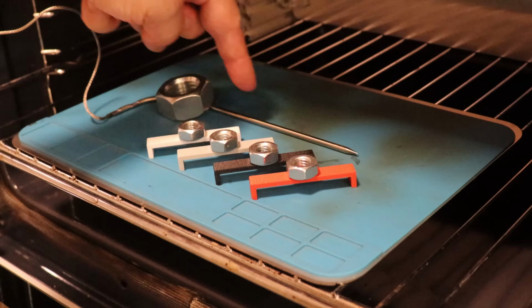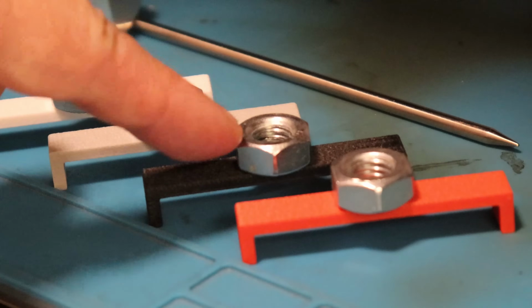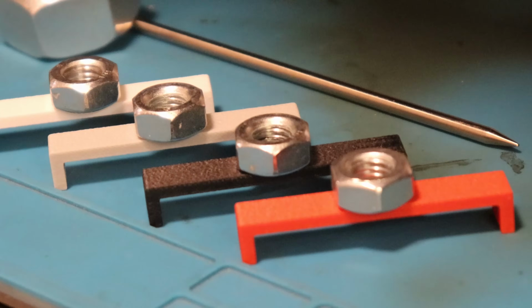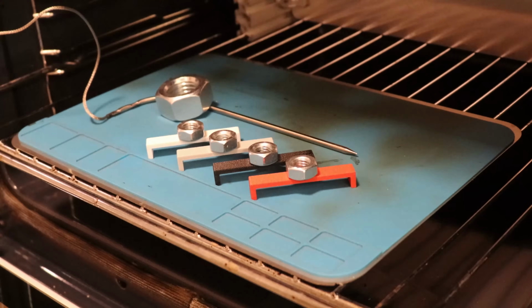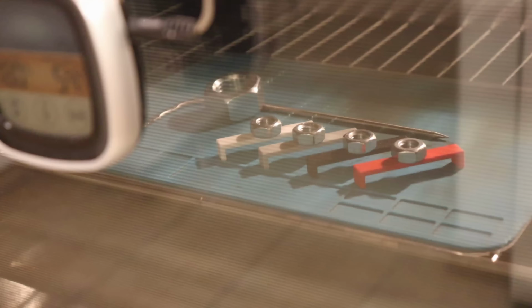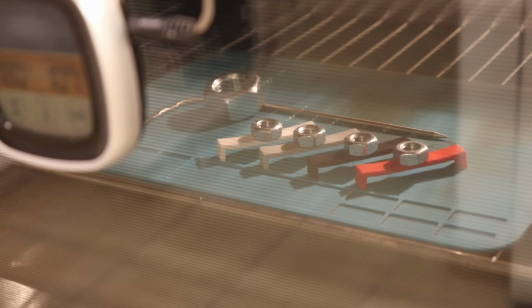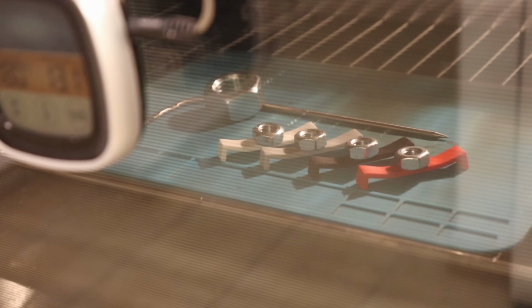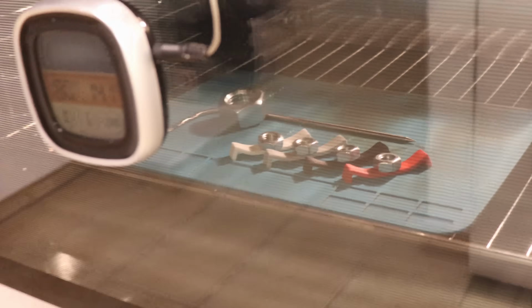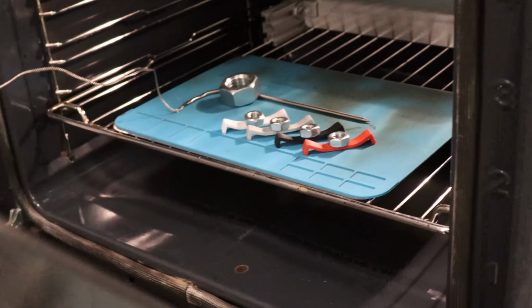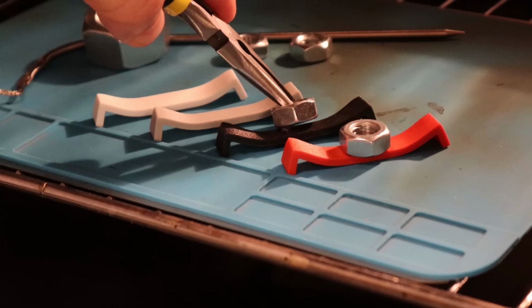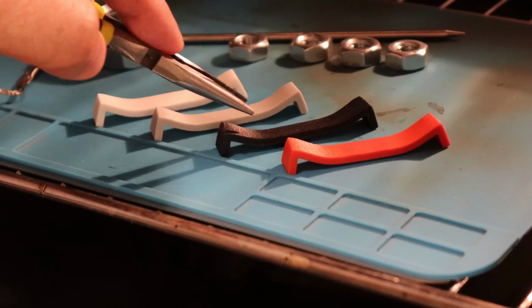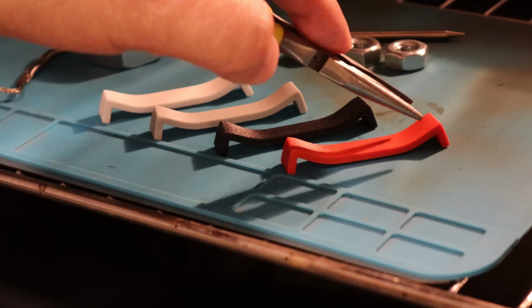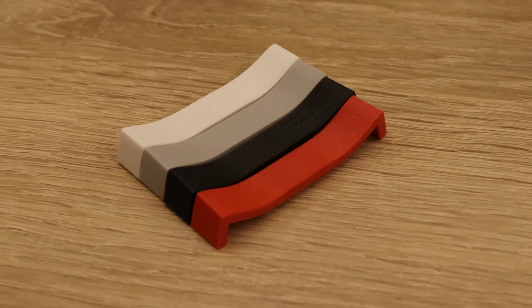The temperature test in the oven. This is the sensor. And I have here an M10 nut as a small load. And I want to record the temperature of the first deformation. This is a time-lapse sped up video. And very similar start of the deformation at approximately 97-98 degrees Celsius. I stopped the experiment at approximately 140 degrees Celsius. Let's see how soft they are. First, let's remove the load. For the filling, very similar, all four. And even their deformation looks similar.